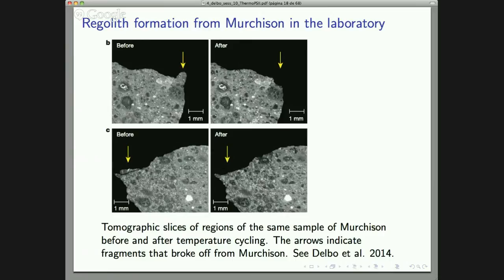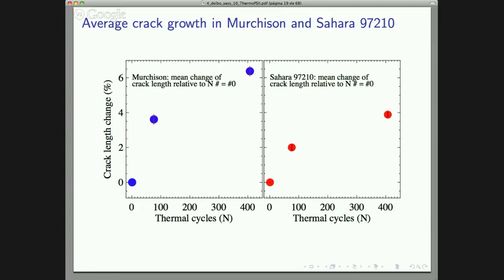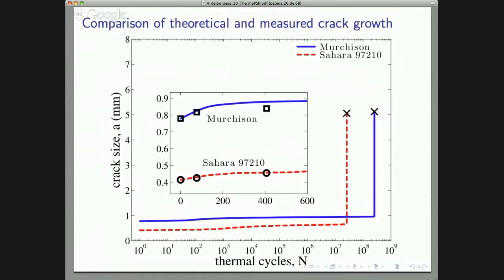We measured many cracks, well, not many, like 30, in Sahara and Murchison. And this is the average relative crack growth in percent after 400 cycles, which is pretty fast. If this would continue this way, every asteroid would be very, very fine regolith. But it is known from the theory of thermal fatigue that the crack growth can level off, and when the crack reaches a certain length close to the length of the object, then you have a catastrophic breakup.